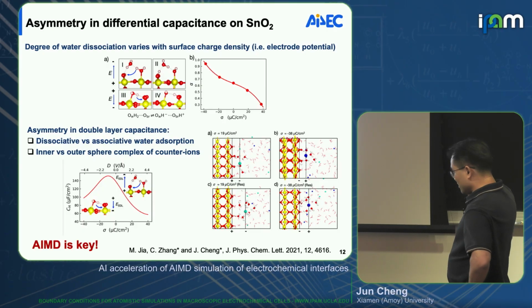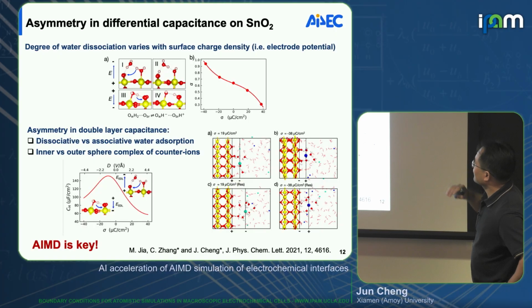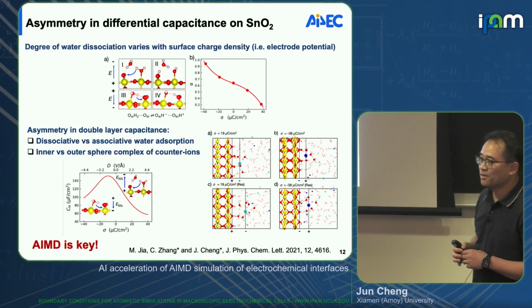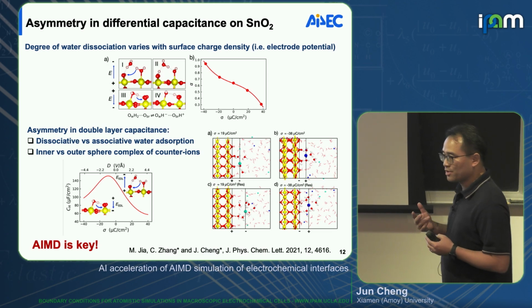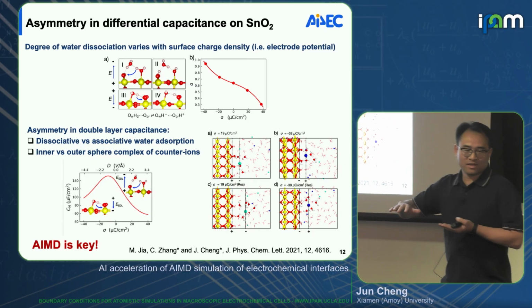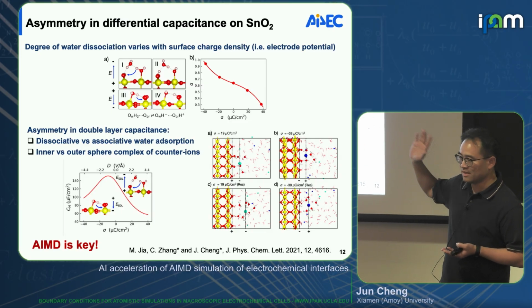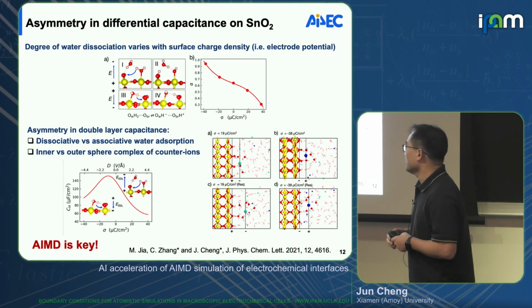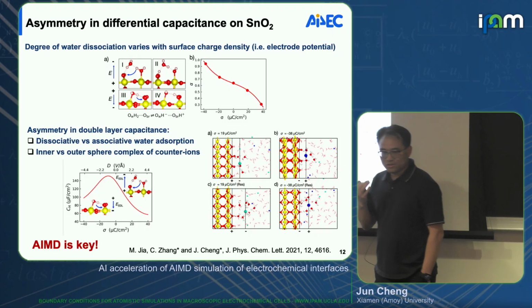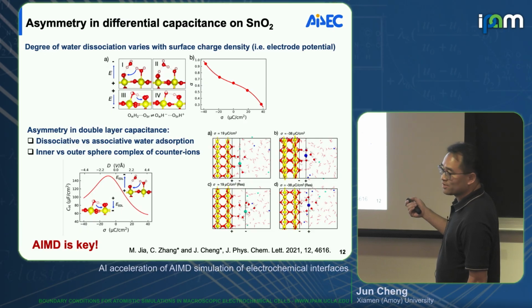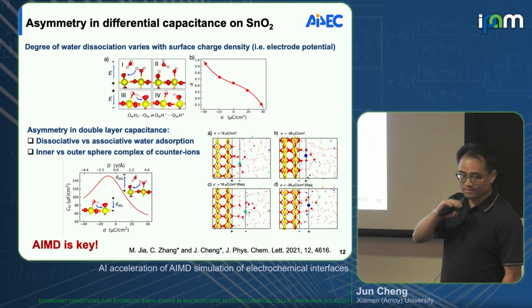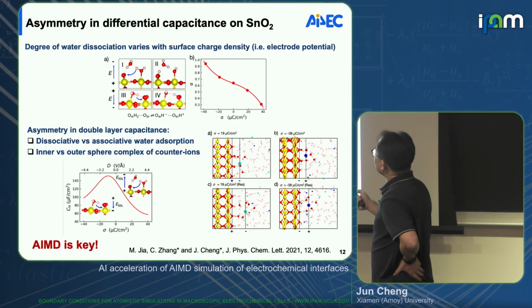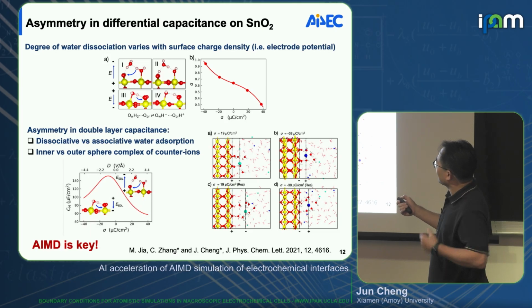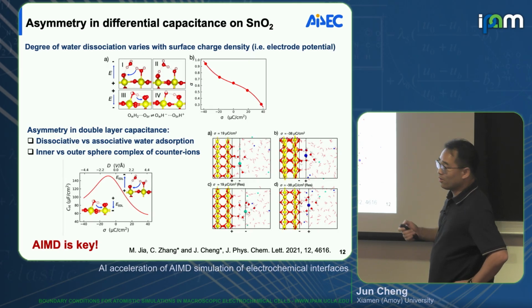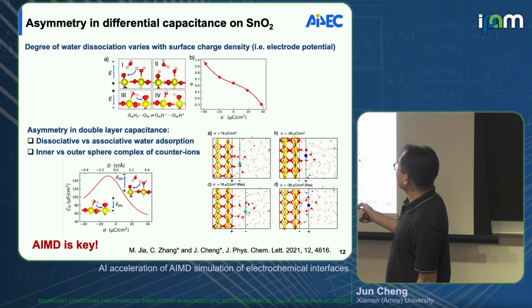Another example, just quickly, is the same for oxide. In this case, that's tin oxide, where the surface charge is not due to the electronic charge, but due to the proton charge. So the charging of the oxide is due to acid-base chemistry. You have proton exchange with the solution at a certain pH, right? You can get charge. And in this case, tin oxide water tends to dissociate at least half, depending on the surface charge density. At the point of zero charge condition, you have around half monolayer of chemisorbed water dissociated. But if you change the surface charge density, you can see this degree of water dissociation also change. So it's sort of whether the water dissociates or not.